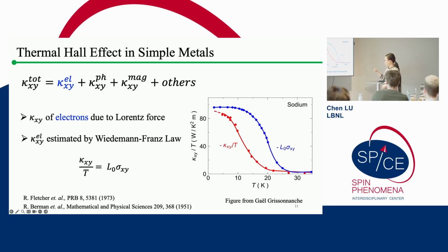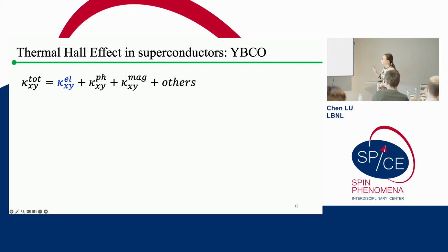Okay, so this is just the regular metals, but actually the first time people thought the thermal Hall effect was super important or useful was to measure another metallic type of material, which is a superconducting material. So here I just use YBCO as an example. One thing I need to mention is, for measuring superconducting material, once it goes below the superconducting transition temperature, all the electrons form Cooper pairs. So if you measure electrical transport, you just get 0, right? But in this case, people thought, okay, we need to find some other type of transport measurement to know the quasi-particle behavior. That's how we use the thermal Hall effect to study the so-called high-temperature superconductors.